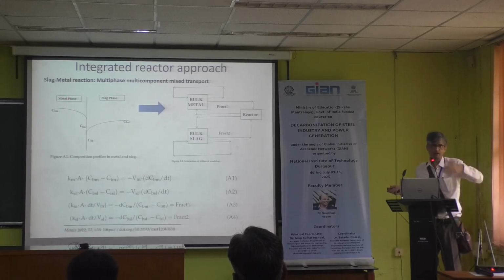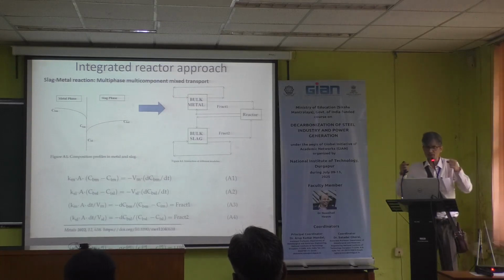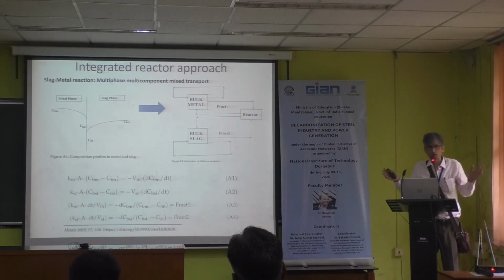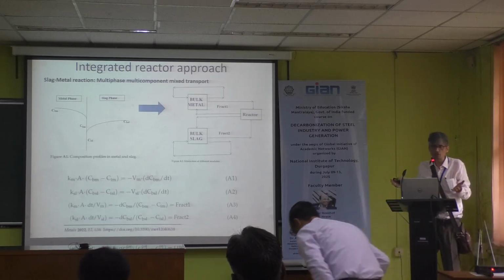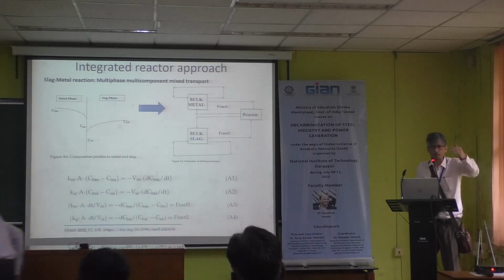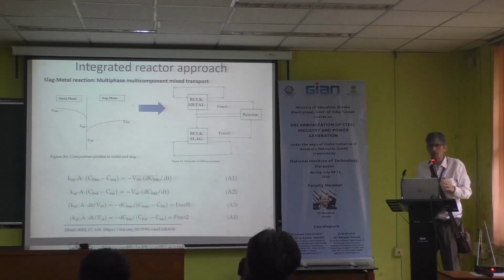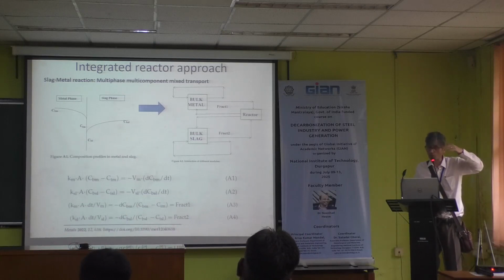some part of the reactor is thoroughly mixed, some part of the reactor is loosely mixed. That depends on the kind of turbulence. For example, in the oxygen steelmaking process, very rigorous energies are evolved because of the evolution of carbon monoxide bubbles from decarburization. Also, the hearth region of the blast furnace can be assumed to be in almost thermodynamic equilibrium between slag and metal. But in the ladle, the slag metal equilibrium may not be there.